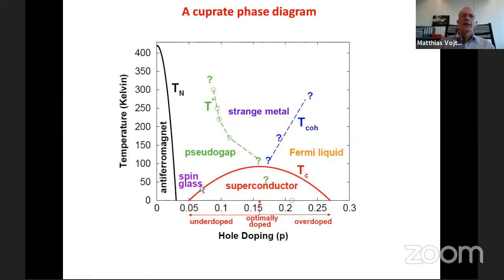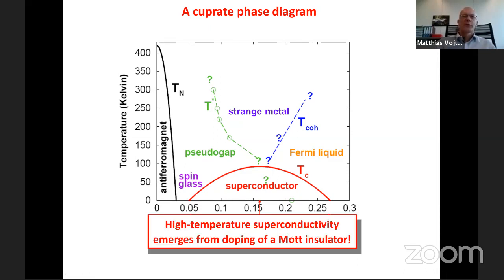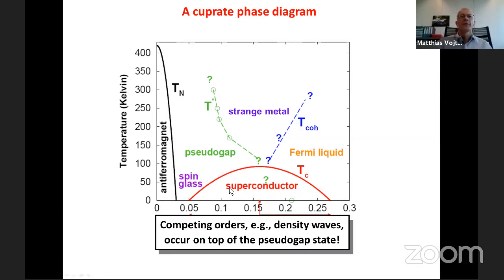What this phase diagram shows is that there are a number of other phases and regimes. And the truth is that the superconducting phase is empirically relatively well understood. But what is not understood are the normal state properties, in particular in the regime of small doping on the left-hand side. But two things are important to realize. First of all, the superconductivity emerges from doping of a Mott insulator. It's not just the physics of a simple weakly interacting metal. The second thing concerns a number of phases which in fact exist in this low doping regime, which I didn't even show in this phase diagram. There are various other orders, somewhere down in the phase diagram, which occur on top of the so-called pseudogap state.